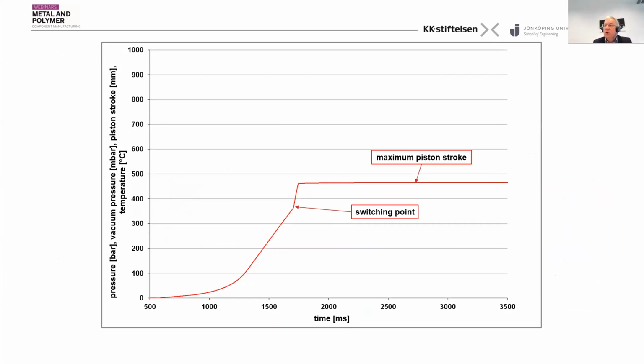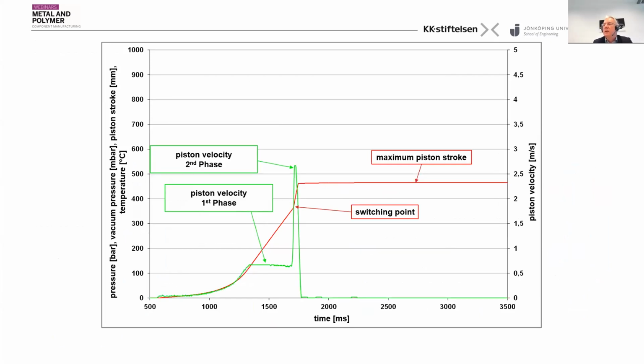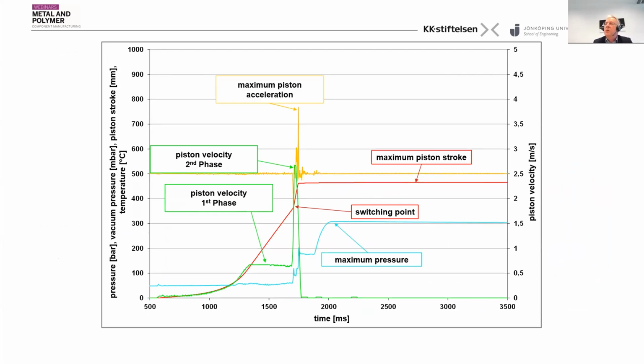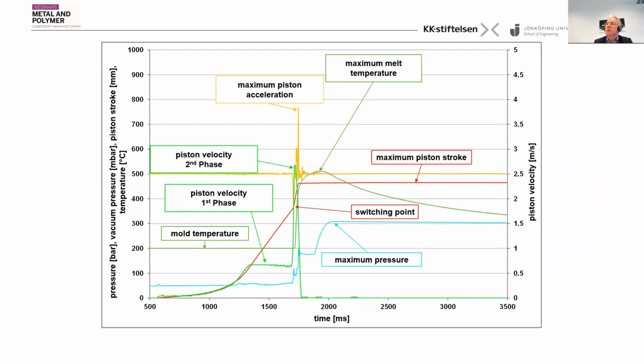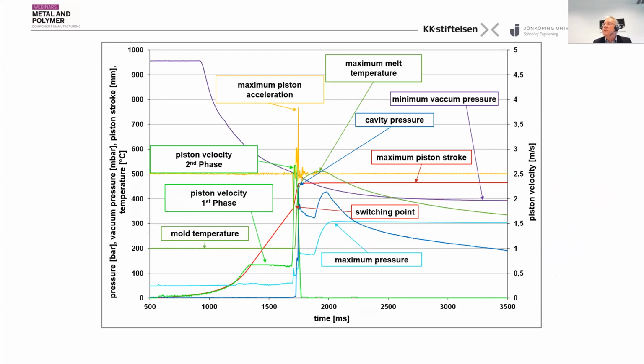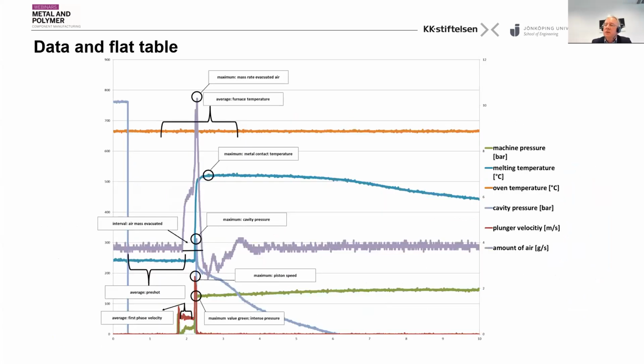And again, you get a shot curve, switch point, and you get a piston velocity. This is what we know, maximum pressure, but now we get a maximum piston acceleration. We get a maximum melt temperature, a mold temperature, a cavity pressure at this position, a maximum pressure, a minimum vacuum pressure, and you can see it is a lot of data coming together. And to understand the data, we need to evaluate the data.